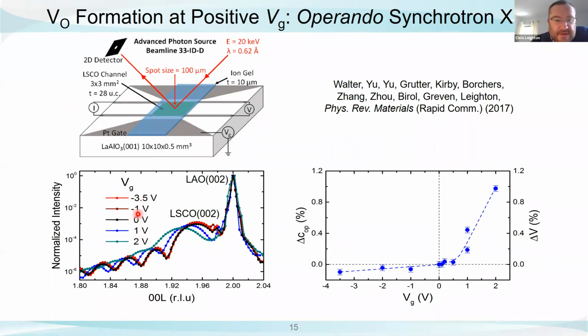And what we basically find is when we apply negative voltages, almost nothing happens in this material. But as soon as we apply even a small positive voltage, the entire peak uniformly shifts to the left. That tells us, of course, that we have a lattice expansion, and that's plotted here. This is the change in the c-axis, or the change in the cell volume as a function of gate voltage. And hopefully this asymmetry I was talking about is now very clear. So we can barely detect any structural change at negative voltage, but by applying just a couple of volts, we get a 1% expansion of the cell volume. It's an enormous expansion of the cell volume.